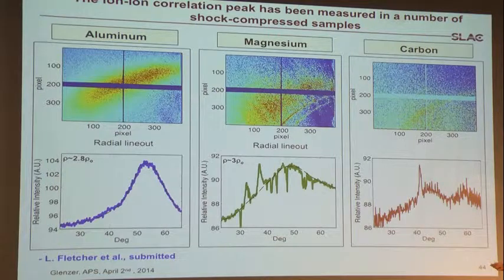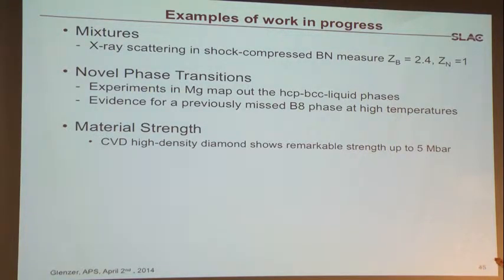I don't want to get too much into this, but I have a few examples where we actually have made significant progress that can give you some examples of the experimental capabilities that are now out there that people can use. So, for example, mixtures. We have done X-ray scattering on shock compressed boron nitride, and we can directly measure now the ionization in mixtures of plasmas with wave number and spectrally resolved X-ray scattering. We have measured novel phase transitions.